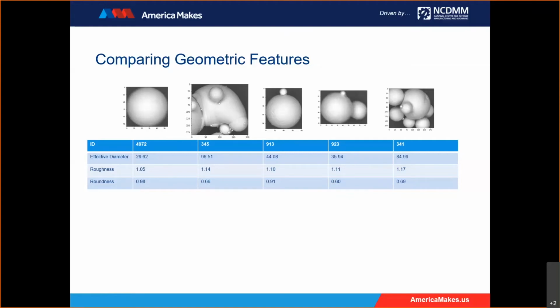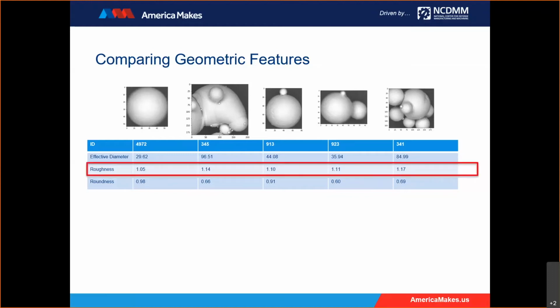In the table below, if we compare geometric features like the diameter, roughness, and the roundness, we can see some differences between these powders. But what's curious is that if we look at the roughness for all these particles, they're about the same. That's the case if we're using a traditional way of measuring particle roughness, which is to use the perimeter ratio.